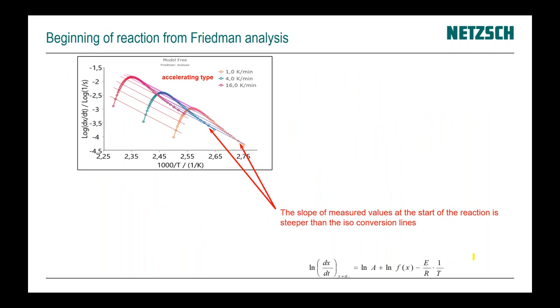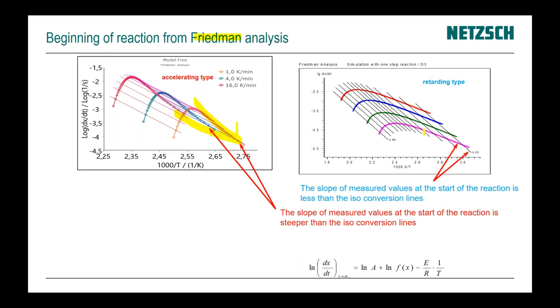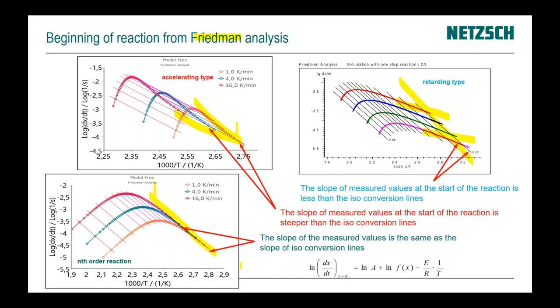The last point is reaction type for steps. The reaction type can be analyzed and found from the shape of the curve. If you do Friedman analysis and look at the isoconversional lines: if the slope of the measured lines is less than the slope of the isoconversional lines, then we have retardation — mostly due to diffusion. If the slopes of both lines are the same, then we have a reaction of N-order type.